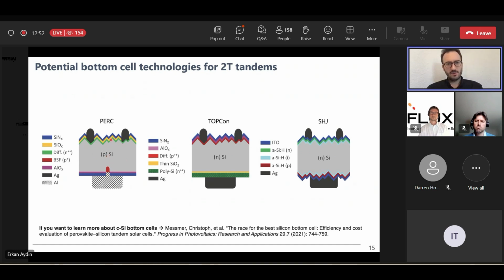Well, the PERC cells are a bit tricky for making a tandem cell because usually we don't have direct access to a recombination junction here. In TOPCon, this is a bit more flexible in that we can do high temperature processing, and the rear side is pretty similar to PERC, but on the front side we can also accommodate indium tin oxide or any other kind of TCO. If we remove the nitride layer, it is possible to make the recombination junction on the TOPCon cells.